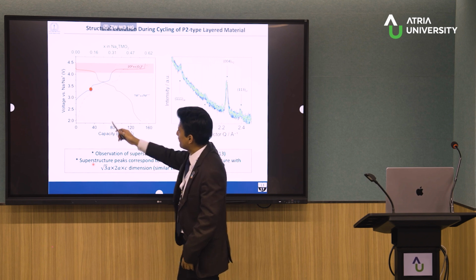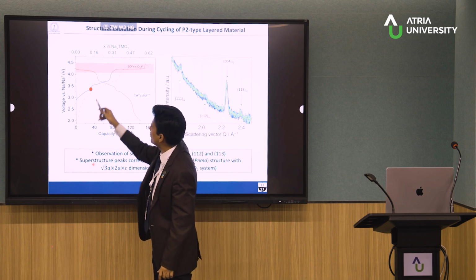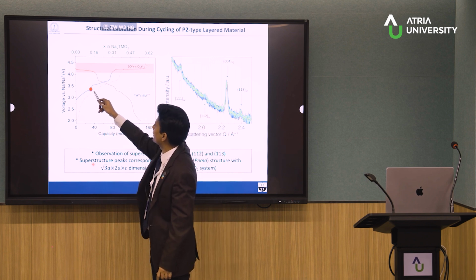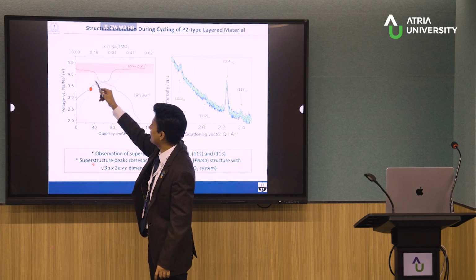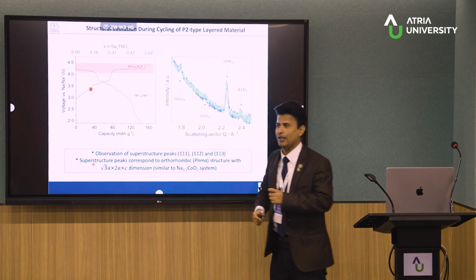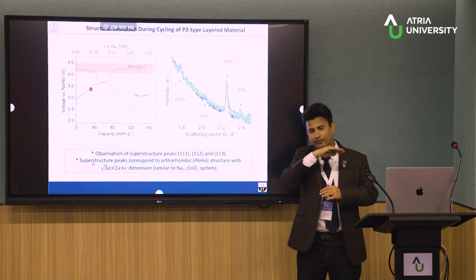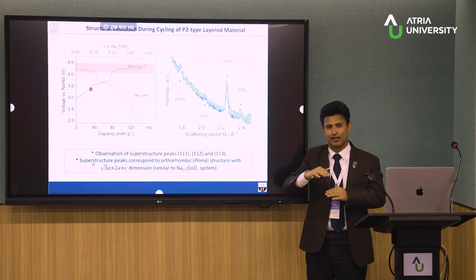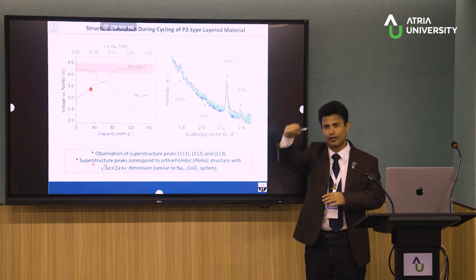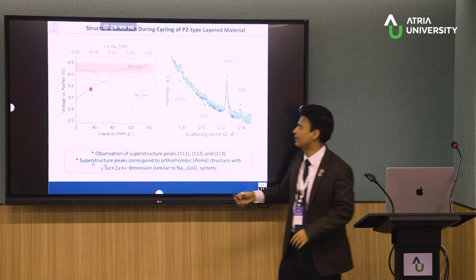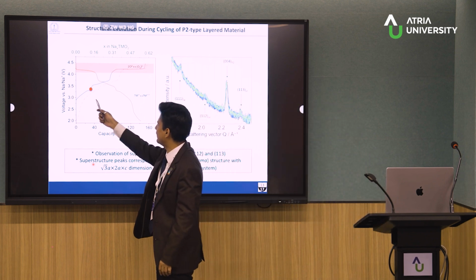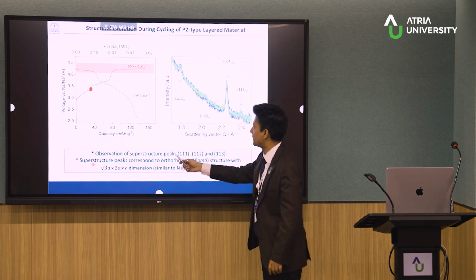Now, at this particular point, around 0.33, some 33% when the reaction is happening, we see a sudden change. This plateau is very well known for different kinds of layered oxide material. In the case of sodium cobalt oxide, we see a lot of step-wise profile. There is a sudden step around this, which is basically because of the observation of a superstructure peak.